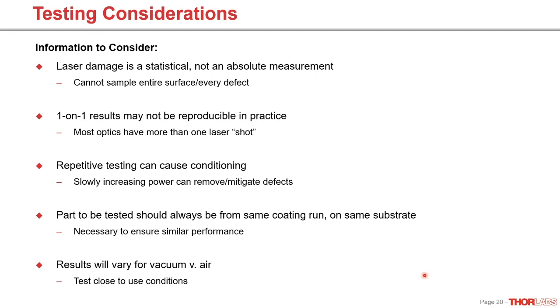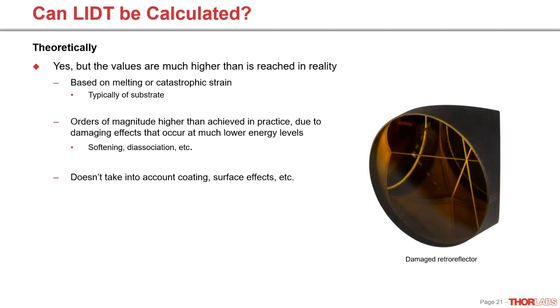One other issue, and this one is a little more esoteric, is if you're planning on building your system in vacuum, you're going to want to test in vacuum, because air is a much better convector of heat than a vacuum is. And this has been well reported in the literature, you're going to see lower damage thresholds for parts in a vacuum. So bear that in mind. Test under your use conditions, or at least as close as possible.